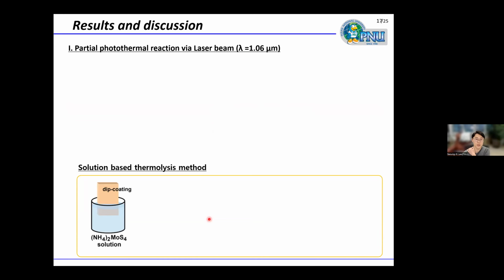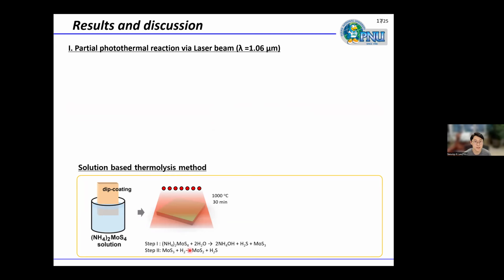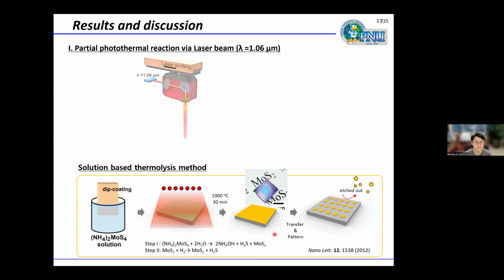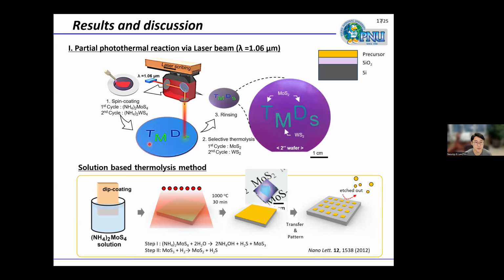Similar to the mechanism in the previous video, we propose a low temperature photothermal treatment method using a laser system. The basic synthesis mechanism is similar to the conventional thermolysis method, as shown in the image below, but there are two key differences. First, we selectively anneal only the desired region using the laser instead of heating the entire substrate with the thermal furnace. Second, we use the fiber laser with the wavelength of 1.06 micrometer.